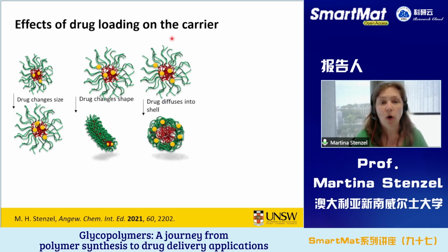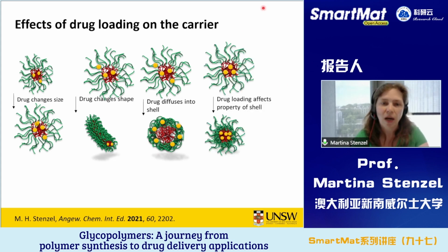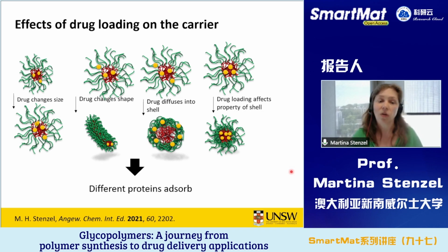Then one thing we observe very, very often is that the drug is not really located in the core. The drug diffuses to the surface. And because it diffuses to the surface, it dehydrates the surface. But even if the drug does not diffuse to the surface, if you add more and more drugs, it can sometimes change the properties of the shell. So this is not always bad news. Very often we observe, if we put in more drugs, it is more efficient. But the message I would like you to take away here is that when we put in drugs, the properties of nanoparticles might change. And when the properties change, you get different protein absorption.